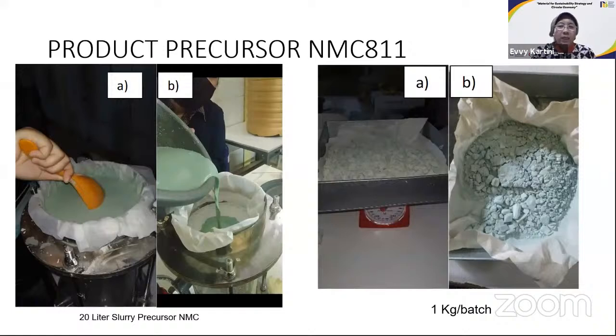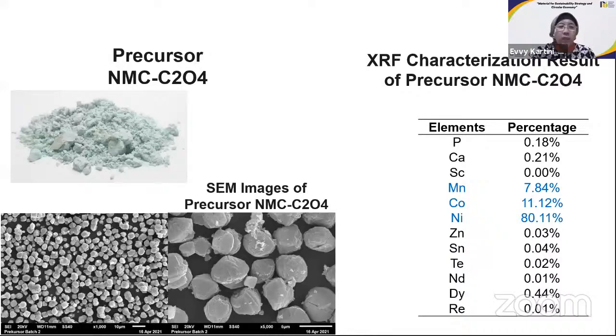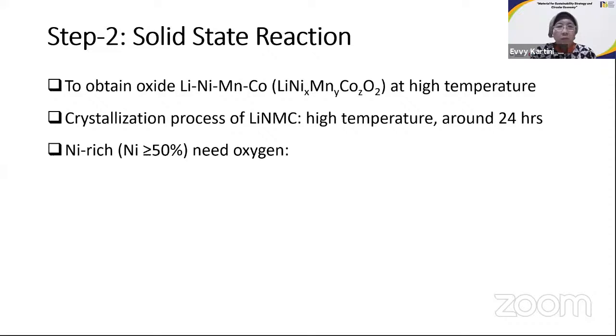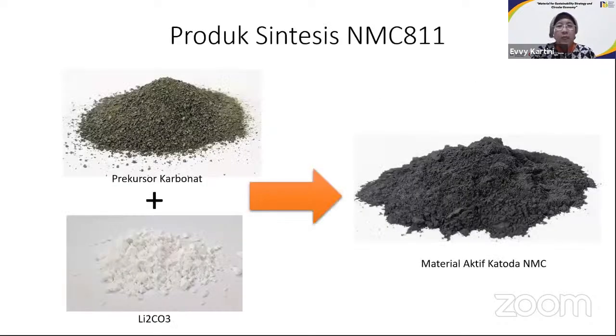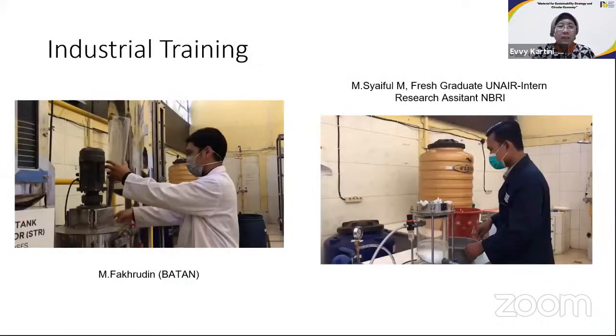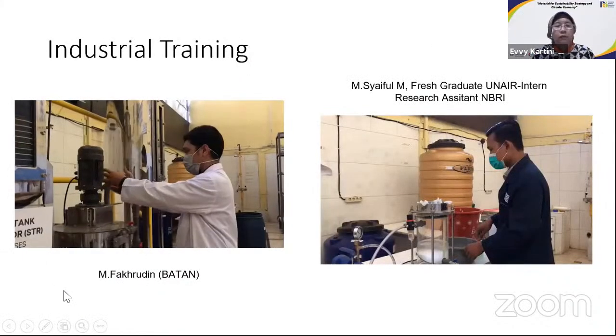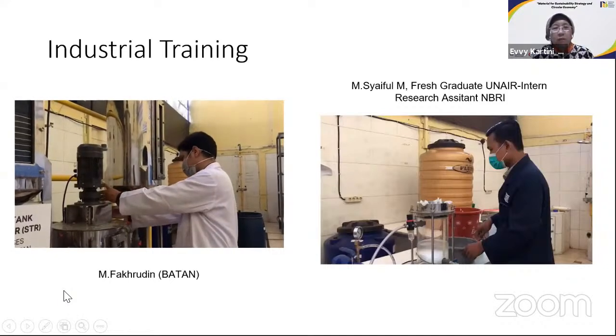But you still need another process. From the precursor, you need to add the lithium. The second process is the solid state reaction. You need high temperature, and you do it for 24 hours. You also need an oxygen environment, the atmosphere in the furnace. So from the precursor, you add the lithium carbonate, and you get the active cathode material. This is an important part of the processing of the NMC.